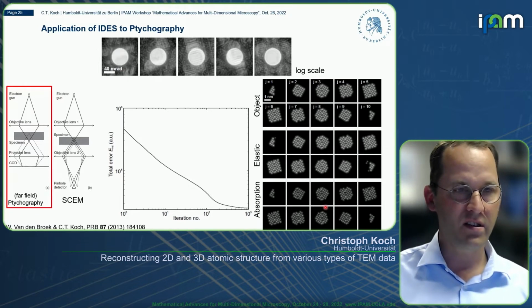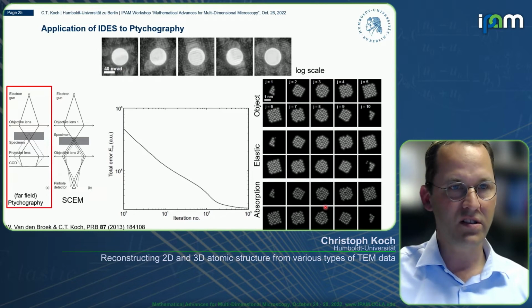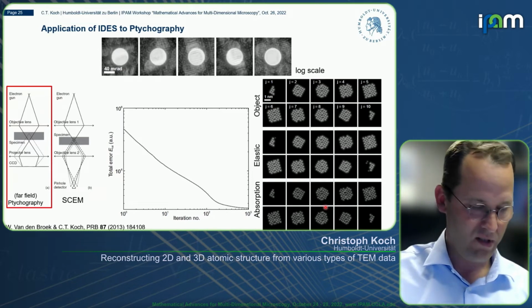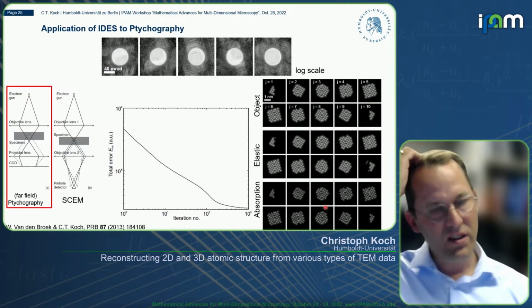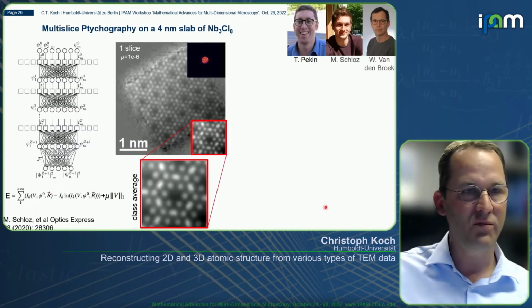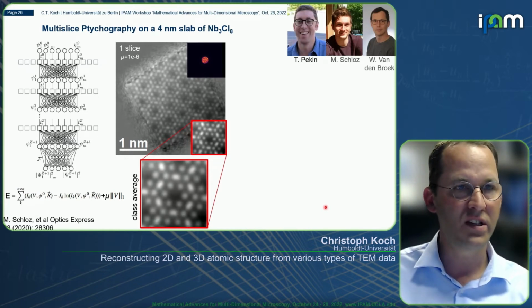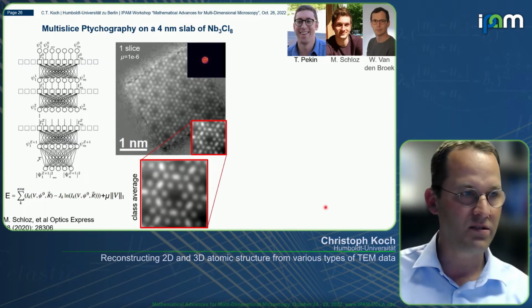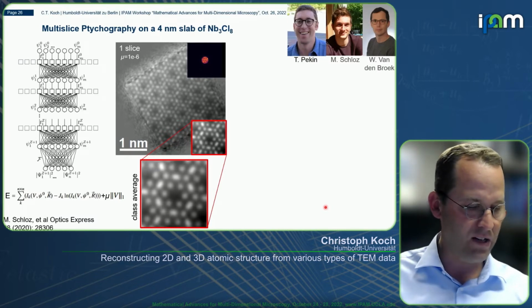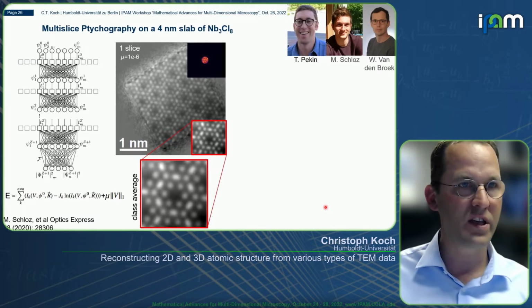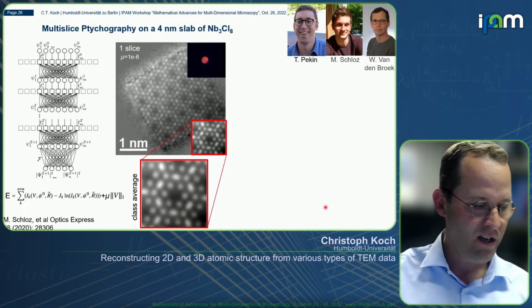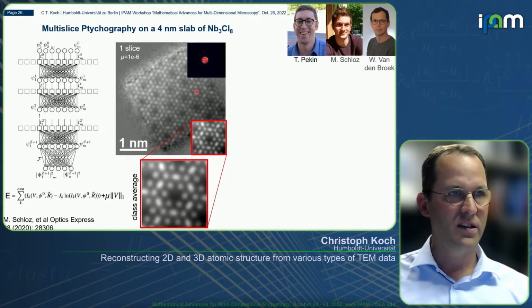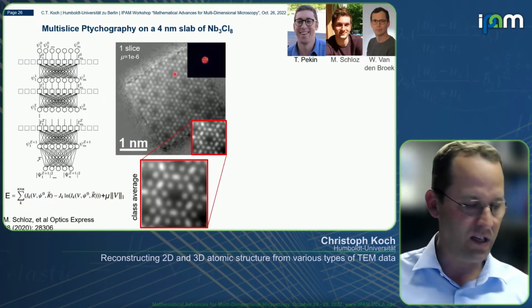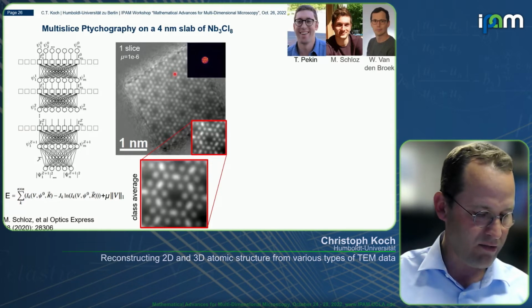So you can really recover more than just the electrostatic potential using this technique, and also in 3D. But that was all in simulation a long time ago, and back then we didn't have the detectors to do this as well as we can now. Before we had our own detector, we collaborated with Dave Muller's group, who gave us some data from this niobium chloride material, where the 2D reconstruction at the time did not reveal the spacing between